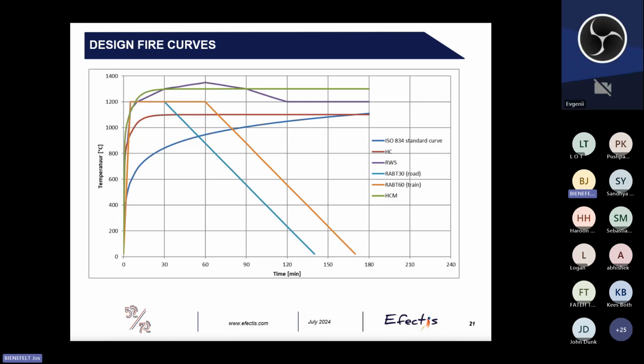But what's also of interest is that the tunnel fire curve has a much higher rise in temperature in the beginning stages. So for instance, the RWS fire curve goes in 5 minutes to 1100 degrees Celsius. And that may have an influence on the behavior of the concrete tunnel structure. So you have a rapid increase in temperature. It's more likely that you will have fire-induced spalling of the structure.